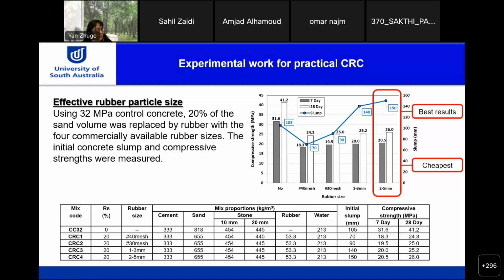And that is compressive strength. You can see very interesting results for 28 days compressive strength. So you have 40 mesh, compressive strength decreased to 24, and you have 30 mesh is about 25, and you have 1 to 3 mm decreased to about 25.2. But for the larger size of rubber used, 2 to 5 mm, the compressive strength actually was higher, 26 megapascals. Okay, so all of them have 20% by volume of rubber.